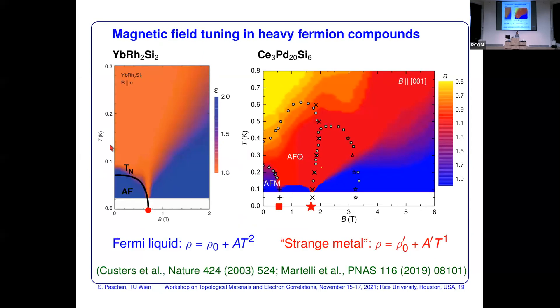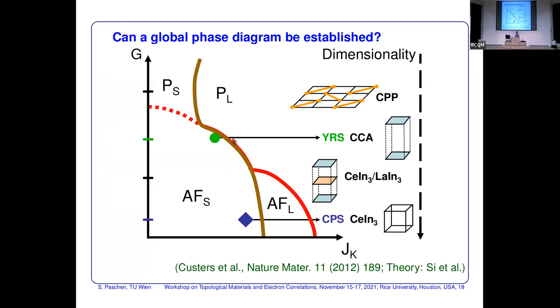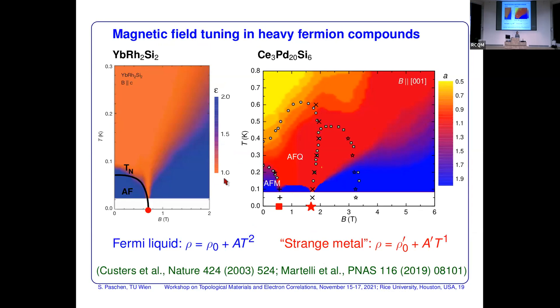Two examples from this approach involve quantum criticality — the lines between phases are quantum phase transitions at zero temperature. If you have a quantum phase transition it leads to quantum critical behavior governing much of the phase diagram in heavy fermion systems. From the top you see non-Fermi liquid behavior that tells you where phases are changing. By optics or neutron scattering you study quantum critical fluctuations and learn about phases — for instance, certain fluctuations indicate Fermi surface reconstructions.